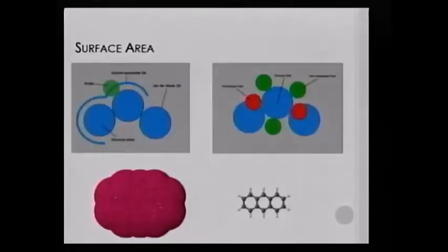Okay. When you put this sphere, where is the origin of this sphere? Is it on the position of the atom, or is it a random position? Basically, when you put the probe around, say this atom, you put in a sphere of the radius of the atom. So you take, for example, the van der Waals radius. You increase it by the radius of the probe.